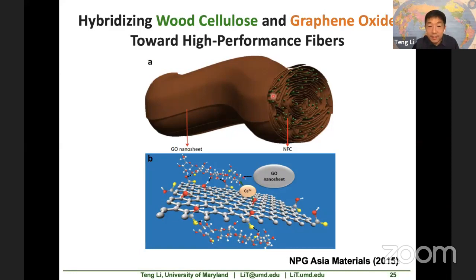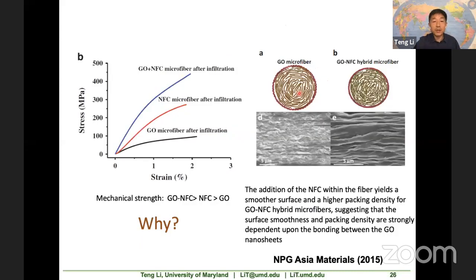And you can use the graphene oxide to make a fiber, high performance, high strength. But you can also add the cellulose nanofibers in it, as shown as this green fibers. It's long, like a long thread threading through all these two-dimensional flakes. Let me show you the stress strain curve of the three different groups of fibers.